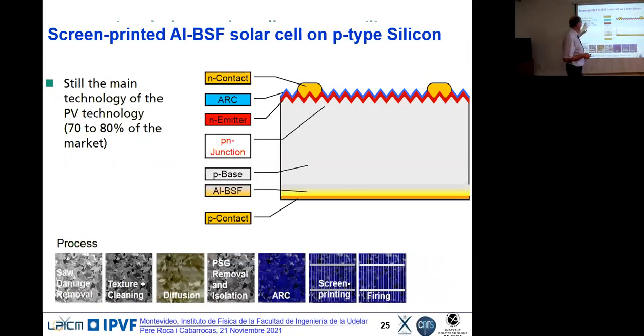I didn't mention the way it's done. You have the crystalline silicon, a thin wafer. You make the n-type junction on the front, put on the reflection coating, and put on the n contact, which is silver. You put on the back aluminum. During the final step, this contact goes through the silicon nitride, and you have diffusion at the back, and aluminum makes a P+, a back surface field, which reduces the recombination of the electrons on one side.